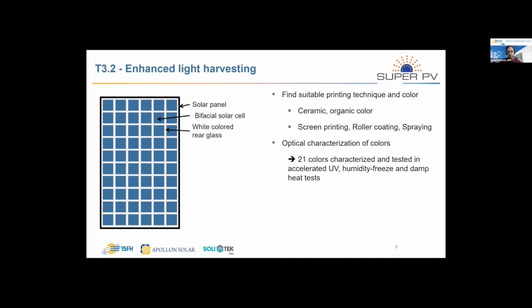And here the first task was to find a suitable printing technique and a suitable color, since there are ceramic colors or organic colors. And then you also have screen printing processes, roller coating processes, or spraying. So we first had to figure out which are the optimal color and printing techniques. And then we performed optical characterization of these colors. And in total, we tested 21 colors, characterized their optics, and tested them in accelerated aging like UV, humidity freeze, and damp heat tests.